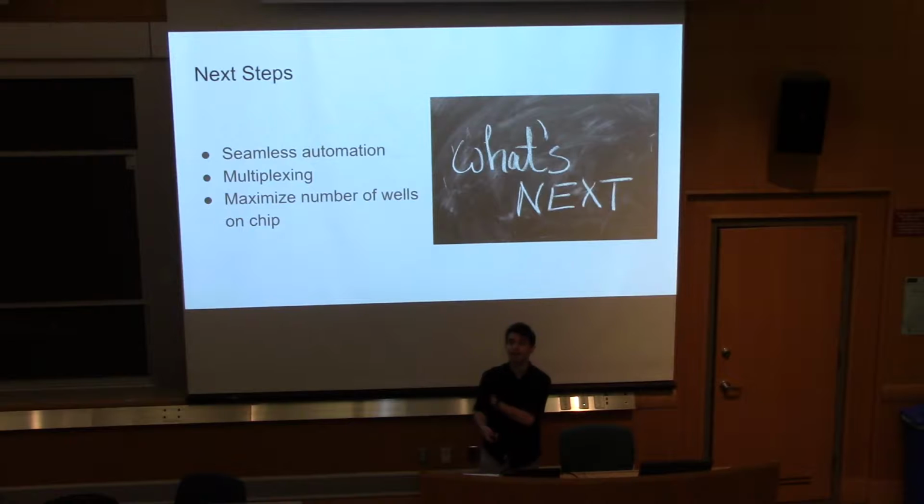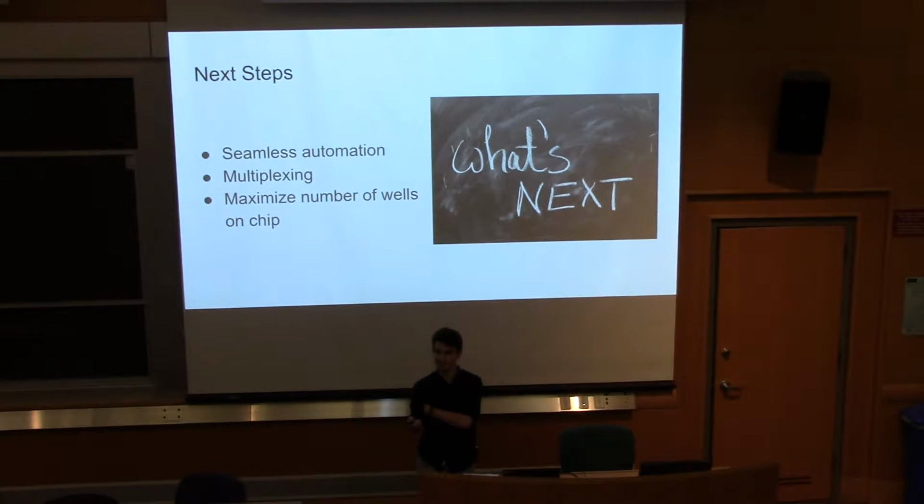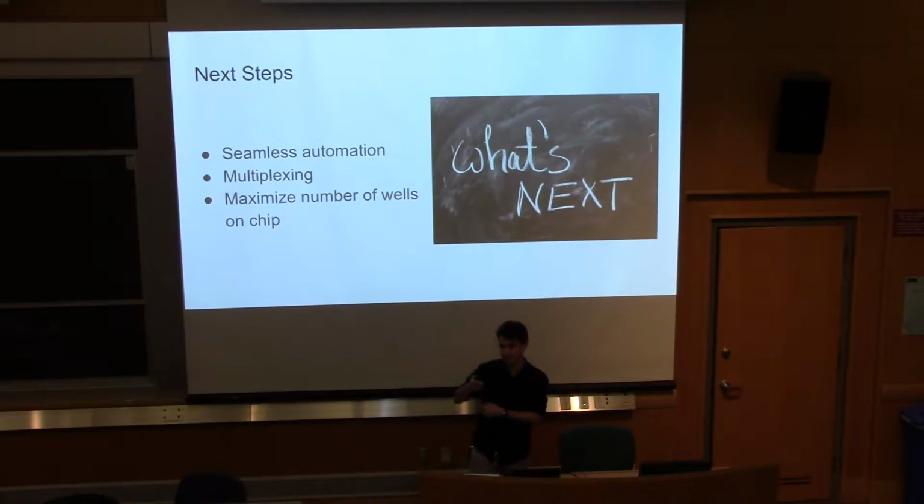But in order to do that, I showed you the PDMS polymer before. We need a better well, because we rip PDMS out of a mold, and if we have wells too small, then the rubber's too delicate and it'll tear coming out of the mold.